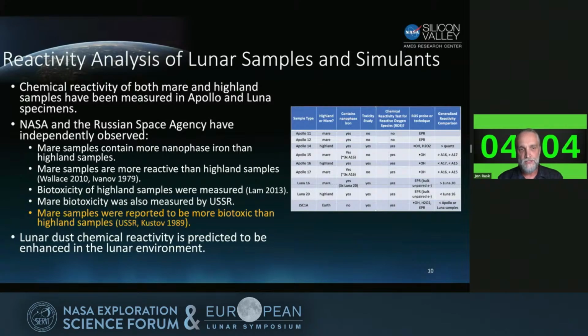And also, there's been a number of biotoxicity studies that have been performed both by the US and Russia. And Mare samples have been reported to be more biotoxic than Highland samples, although the Russian studies were a little bit flawed because some of their particle size controls were less effective than the LADTAG studies, which were highly particle size controlled. And so our take-home message here is that lunar dust chemical reactivity is predicted to be enhanced in